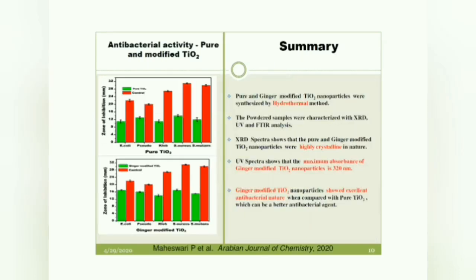When we go for the antibacterial studies, we can see that the gingerol in the ginger has enhanced the activity further. You can see from the zone of inhibition for Staphylococcus aureus, it has now increased to 17 millimeter.